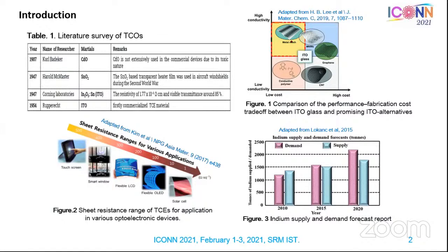If you see figure 1, metal meshes are very highly conductive, but they possess very low transparency, though the cost is very low. But coming to conductive polymers, they possess low conductivity, but the transparency is very high. So ITO is the promising material compared to all, and we use ITO in different devices based on the sheet resistance. For low sheet resistance, we use it in solar cells. For higher sheet resistance, up to 500, we use it in touch screens and LCDs.